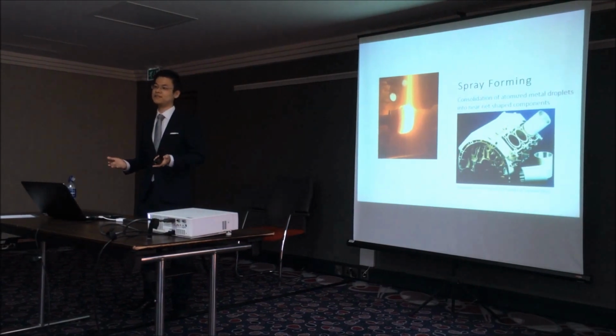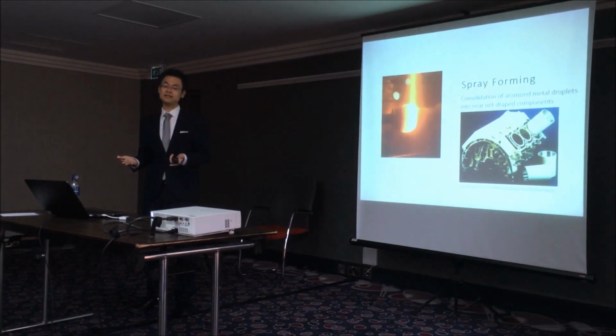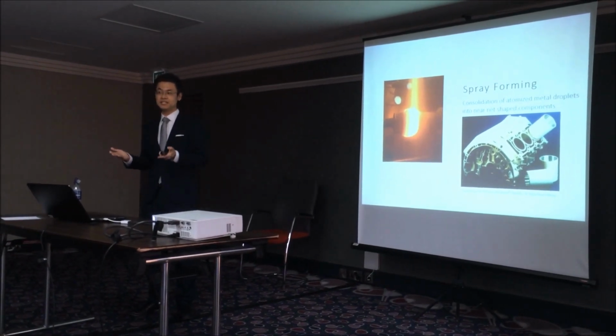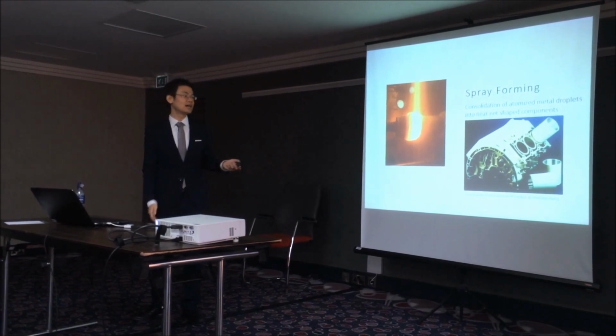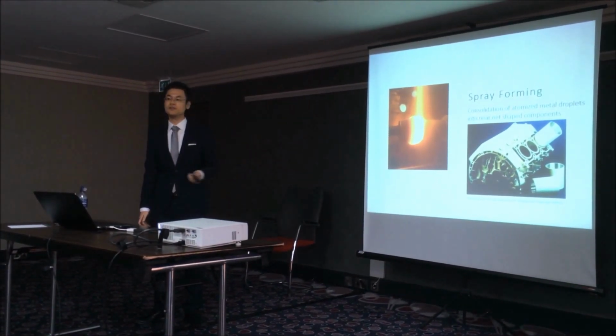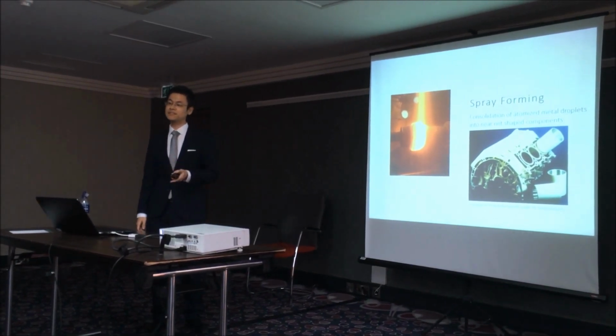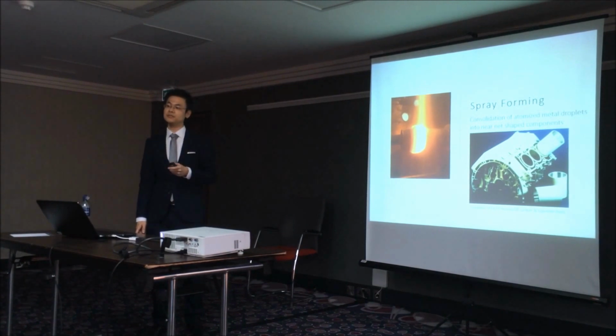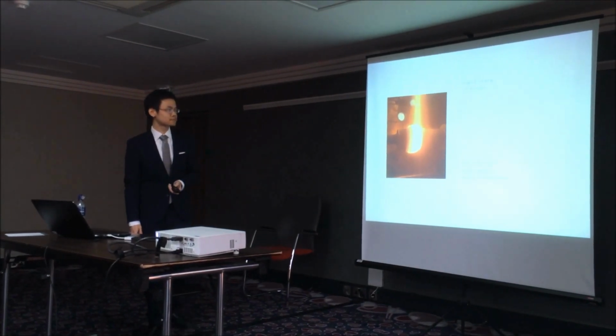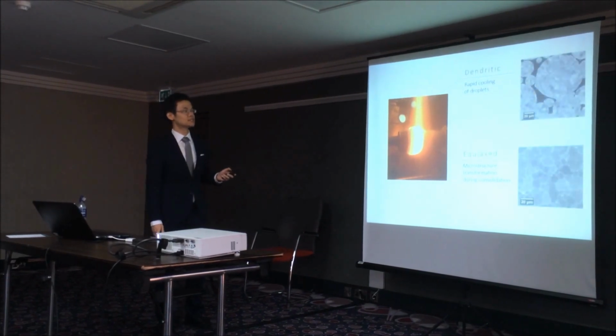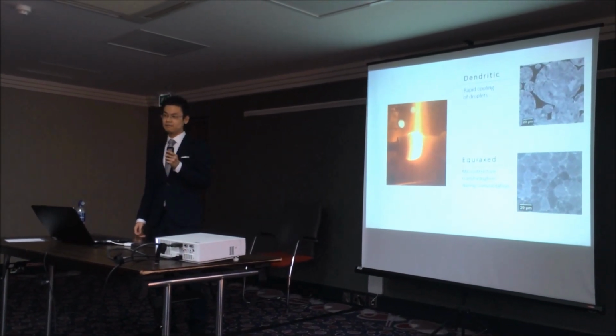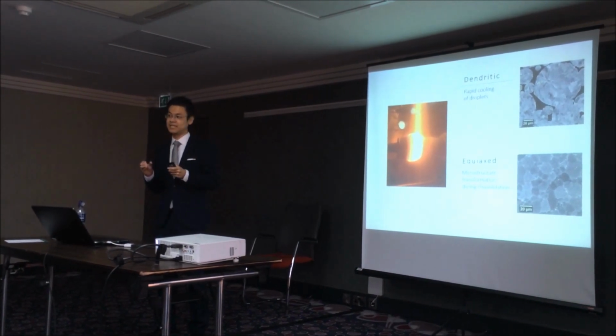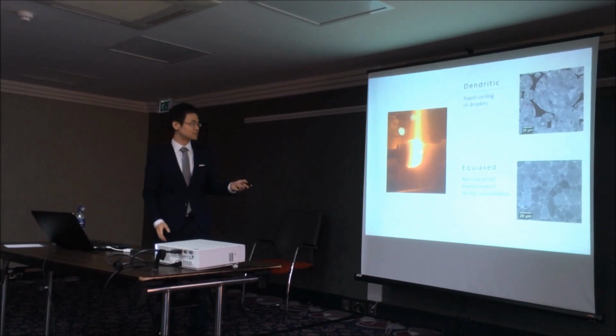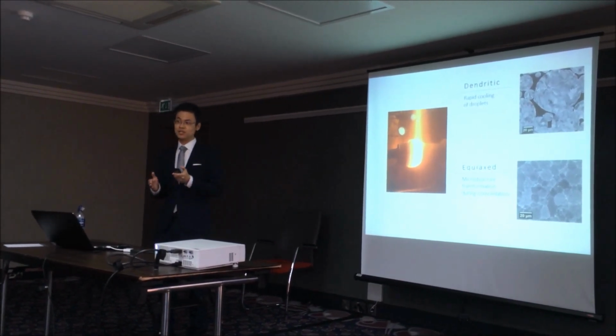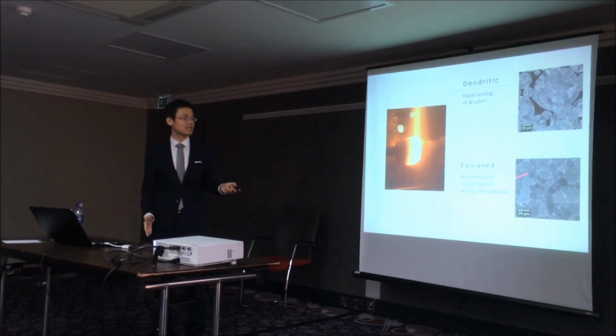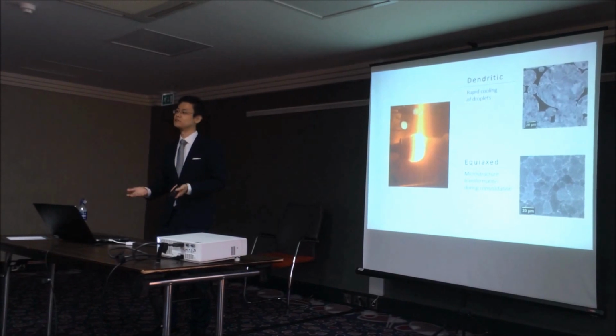Therefore, spray forming offers benefits in terms of flexibility and the reduced and simplified steps to produce near finished product shapes, and has found applications in industry, such as to produce the cylinder liners for automotive engines. Now, the benefits of this technique extend to the material properties of the products. Due to the high cooling rates of the droplets, dendritic and cellular microstructures are formed within these droplets at a very fine scale. Now, when these droplets are deposited and consolidated, this microstructure transforms into a fine equiaxed microstructure, and therefore enhancing the material properties.